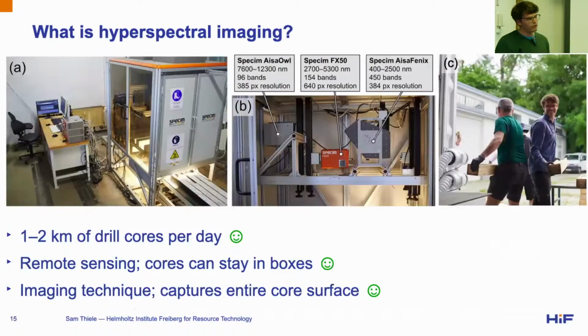So this is an example of a drill core scanner. This is the one that we use, the SpecIm SisuROCK. Inside this cabin here, you can see 3 different hyperspectral cameras, because unfortunately there's no single camera that can measure the entire wavelength range that we care about with rocks. Normally you have one for the visible near infrared and the shortwave infrared, so that's good for clay minerals, iron oxides, chlorites, phyllosilicates. Then a separate camera for the midwave infrared and a third one for the longwave infrared. And you need those latter 2 if you want to start looking at silicate minerals.